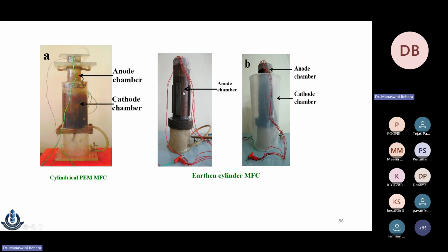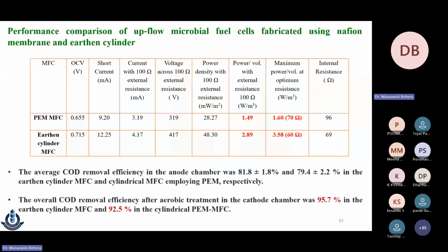Then we compared the treatment efficiency of these two reactors. You can see here, in the case of the earthen cylinder MFC, 2.89 watt per meter cube of power was generated, whereas it was 1.49 with the proton exchange membrane. The internal resistance was quite low in the earthen cylinder MFC. And you can see that the COD, the chemical oxygen demand, the organic material removal efficiency, was higher in the earthen cylinder MFC. So we found that this earthen material based ceramic membrane which we prepared is a good alternative to the very costly proton exchange membrane that is made up of polymeric material.